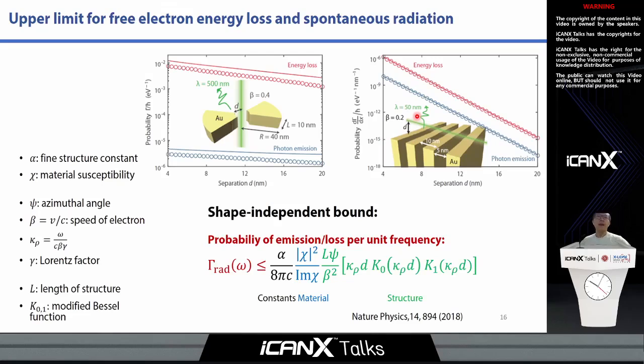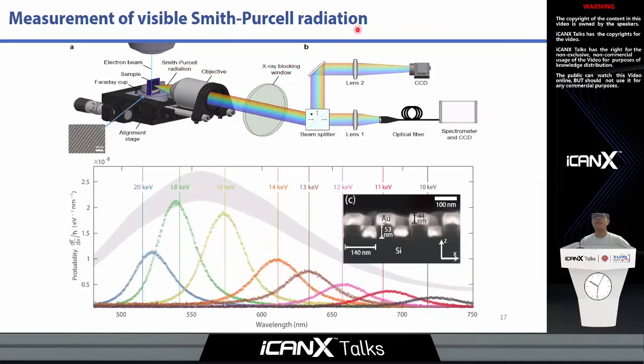We test our upper limit theory by measuring the Smith-Purcell radiation. Smith-Purcell radiation is a process where a free electron passes through a periodic structure at a grazing angle and generates radiation due to momentum conservation. We test our upper limit theory by measuring the free electron radiation from a one-dimensional grating made of silicon and gold at different free electron energies. What's interesting here is that we find that the envelope of the measured emission spectrum has a peak, and it is captured by our upper limit theory.